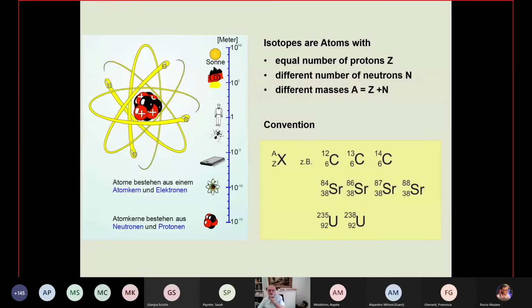Now, the problem, which has already been mentioned before, is that on the way from the ore source to the final objects, you have chemical separation processes, you have the smelting of the ore, and maybe also you have some alloying and so on. So that is a problem for the provenance determination based only on the chemical composition or even a trace element pattern.